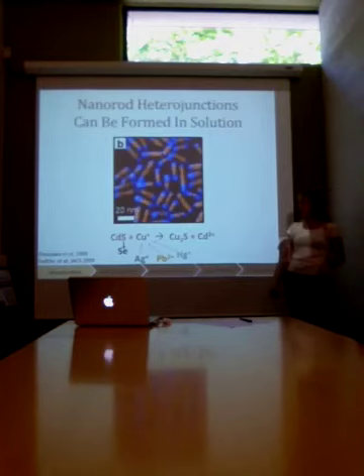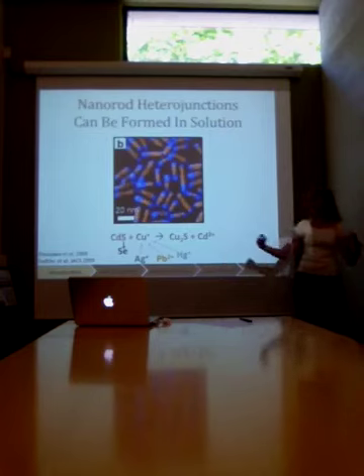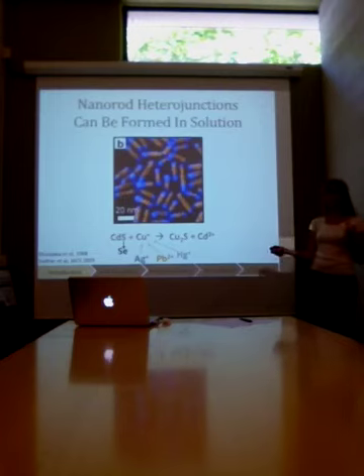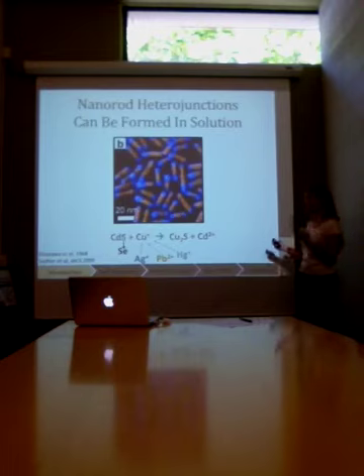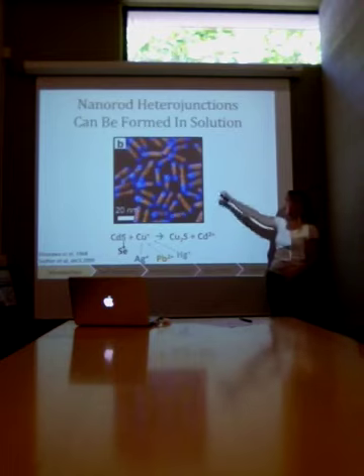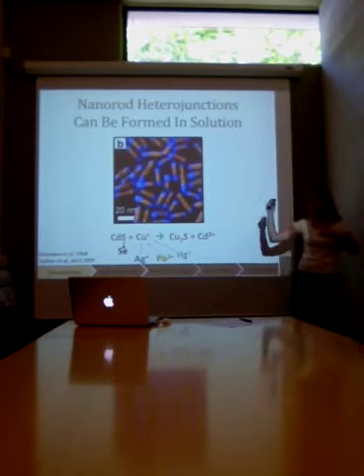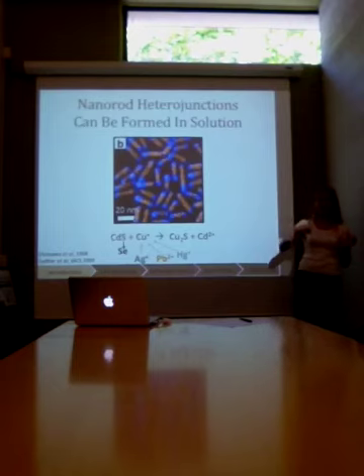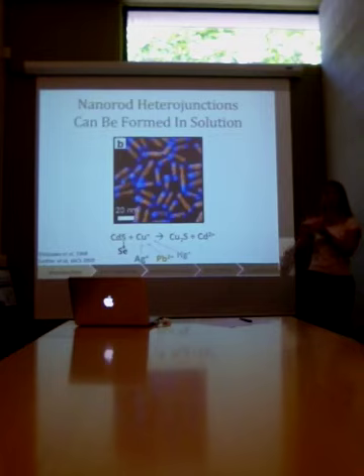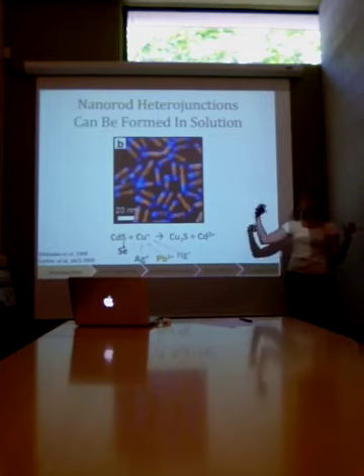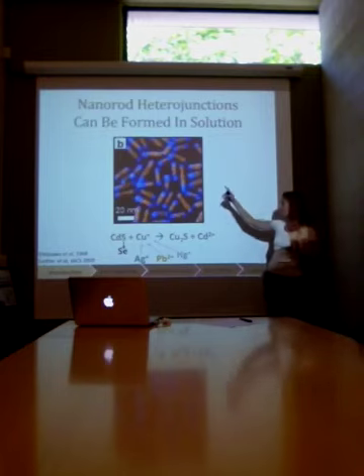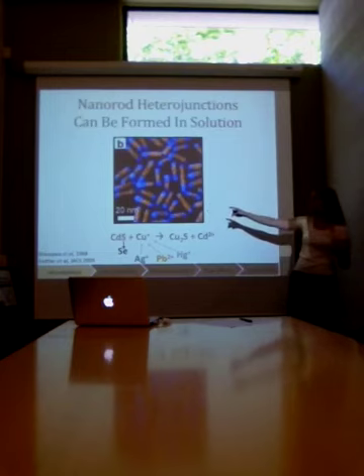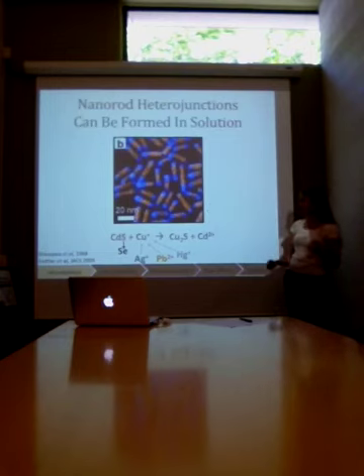Shiozawa et al. showed this in bulk systems, or large-scale systems, in 1968, and recently Sattler et al. showed it using cadmium sulfide nanorods. So in his experiment, he had cadmium sulfide nanorods floating in solution, and he added in copper ions. It's energetically favorable for the copper to trade out with the cadmium, and this happens selectively from the ends of the nanorod. So in this false color image, the blue is copper sulfide, and the yellow is cadmium sulfide.